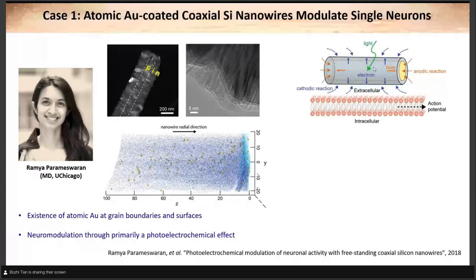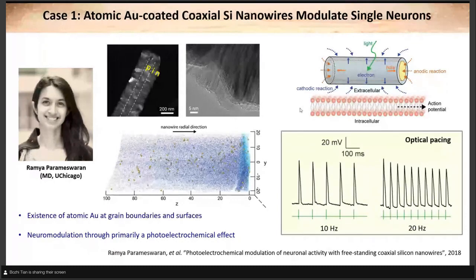We have a coaxial silicon wire, and we also have a piece of cell membrane from a neuron. Now, upon light excitation, you have, of course, both the anodic and the cathodic reaction, but the cathode part is closer to the cell membrane. So the cell mostly feels the impact from the cathode, which tends to reduce the polarity of the cell membrane, and in the example cells can elicit action potentials. So that's exactly what Ramya did. She delivered those light pulses with different frequencies, say 10 hertz or 20 hertz, and we can actually modulate the pace of the neuron firing frequencies at the target frequencies.